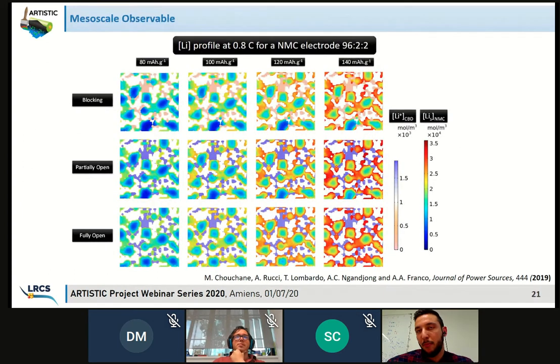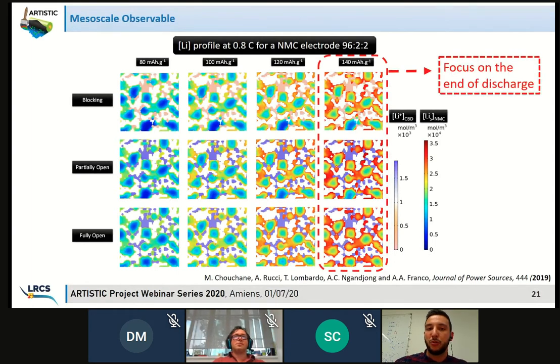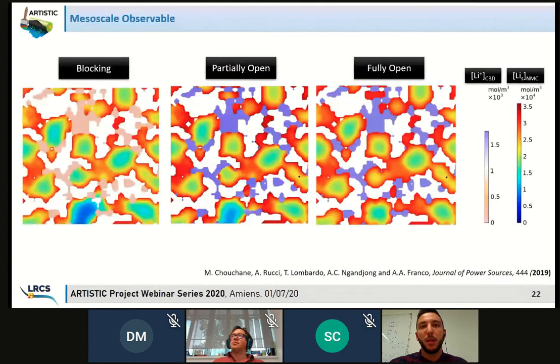So one of the best thing about modeling is that you can have access to all these different observables at each time in your system once you have your simulation done. Here is a map of lithium concentration in the solid and in the CBD at different discharge time for each different hypothesis. So we will have a closer look at the end of discharge because that's where the differences are the most dramatic. So here are for the three different hypotheses: blocking CBD, partially open CBD, and fully open CBD. So as you can see, the CBD here, when it's blocking, the concentration is equal to 0, whereas it's around 1.5 for the fully open and partially open case.